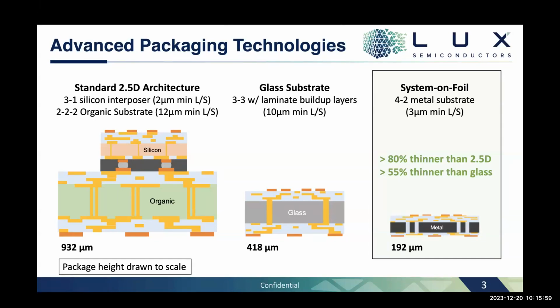I should probably be able to get through the rest of this in 5 minutes or so. What we're showing here is just a cross section of a somewhat equivalent layer count, incorporating the difference in line and spacing of your two common or emerging advanced packaging technologies, the 2.5D and the glass substrate, alongside the system on foil. And all three have cores and then either build-up layers or pattern interconnect layers on top and bottom. And what's shown here is the difference in form factor, really the significant reduction in thickness over both platforms.